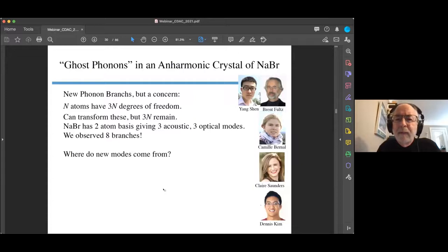I didn't show you the phonons from sodium bromide, but we found something new. We found two new branches in the phonon dispersions of sodium bromide. If you have N atoms, you'll have 3N degrees of freedom, which you can transform by a linear transformation like Fourier transforms to get normal modes out, but you'll still have 3N of them.